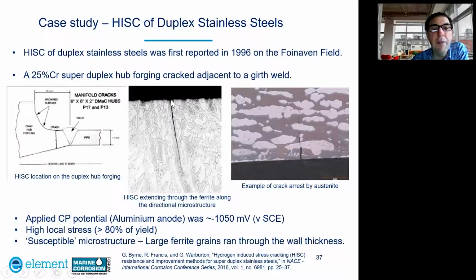And this photograph shows the HISC here running along the ferrite phase of the duplex structure, and the crack was not interrupted by any austenite islands, so it was allowed to extend through the complete wall thickness of the hub.